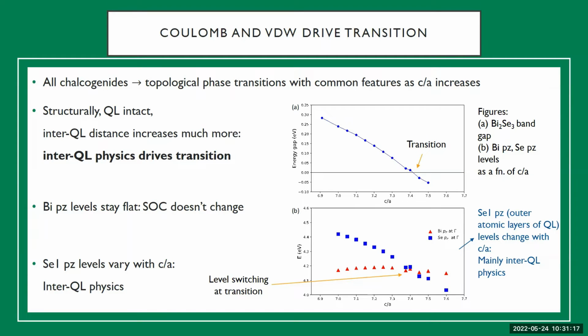So in the beginning, the red triangles, which are the bismuth PZ levels, are considerably below the selenium PZ levels, which are the blue squares. And as you increase the C/A ratio, which amounts to applying strain, they start getting closer together, and at some point they exchange, they flip, and beyond that point, it's a trivial material. Whereas initially, for low values, towards the left of the graph, you have a topological system.